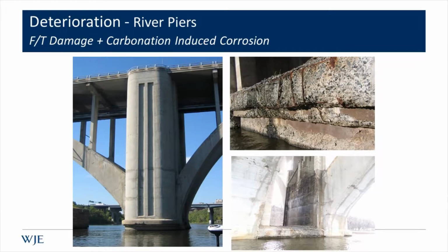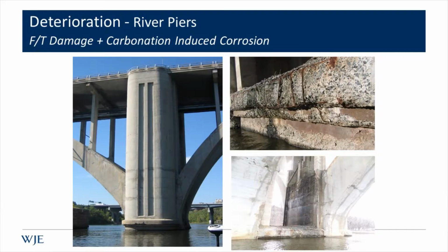At the river piers, the outward-facing sides of the river piers were generally in good condition, and there was some carbonation-induced corrosion, but as you can see in the image, all in all, they were in pretty good shape. On the interior surfaces, particularly in areas where deck drainage was poor or diverted directly onto some of these surfaces, there was some pretty heavy freeze-thaw damage, as in the image in the lower right. Hopefully you can see that. And then particularly at the river line, there was some very deep freeze-thaw damage, which I'll get into a little bit later. However, the land piers were a bit of a different story.